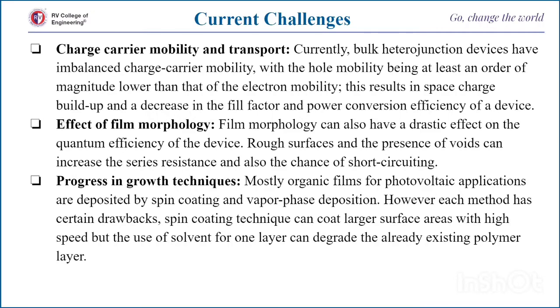Effect of film morphology. Film morphology can also have a drastic effect on quantum efficiency of the device. Rough surfaces and the presence of voids can increase the series resistance and also the chance of short circuiting. Progress in growth techniques: mostly organic films for photovoltaic applications are deposited by spin coating and vapor phase deposition. Each method has drawbacks. Spin coating can coat large surface areas with high speed, but use of solvent for one layer can degrade the already existing polymer layer.